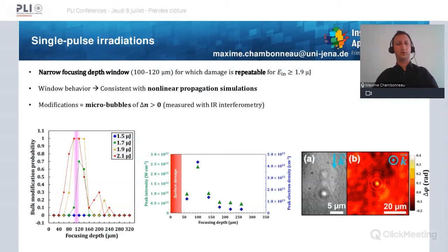So what now about the reality of experiments? Well, to answer this, we have carried out some damage probability measurements at different focusing depths and input pulse energies. And what we have seen is that it was possible to produce some repeatable damage inside silicon, with 100% damage probability, in a very narrow focusing depth window around 100 or 120 micrometers.